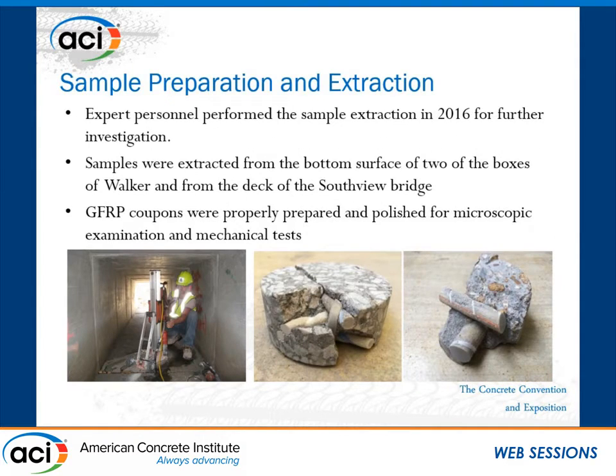In 2016, expert personnel extracted several concrete cores from these 2 structures at different locations. The samples were taken from the bottom surface of the GFRP box culverts, which logically has been exposed to more moisture, and also from the bridge deck of the Southview Bridge.